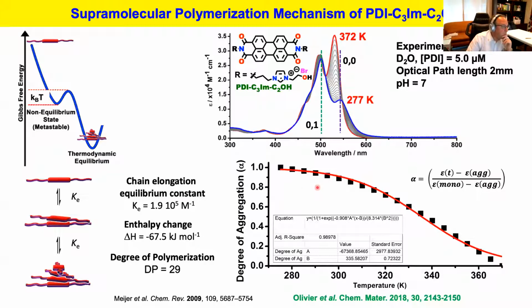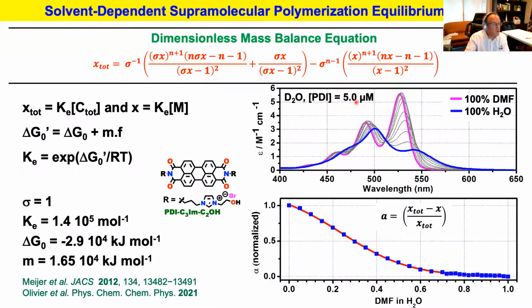So remember the little red rectangle that I showed you in the last slide, preformed assemblies. Again, by using this model, I won't go into too much detail, but we can extract thermodynamic parameters, and also structural parameters such as the degree of polymerization, the average number of building blocks that are stacking in one pi stack, okay? So that's just to show you that any subtle change in temperature, for example, will disrupt the optical properties of this assembly. So that's one important parameter to keep in mind. Now, of course, we can also show how solvent can extensively modulate the optical properties of this small aggregate in solution. We all have heard about good solvent and bad solvent. In that specific case, good solvent will be DMF.